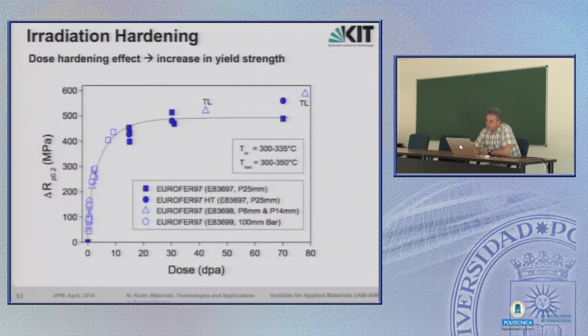That's the dose dependency. If we irradiate again 9% chromium steel and measure only the irradiation hardening over the doses, you see at the beginning of the irradiation, up to maybe 20 dpa, there is a very steep increase of hardening. And from 20 dpa on to higher levels, the increase is not as high anymore. Temperature was constant here, in the range around 300°C. That's the effect of irradiation hardening on tensile properties. If you know that, that's all you need to know, because there is not much more to know except very tiny details.